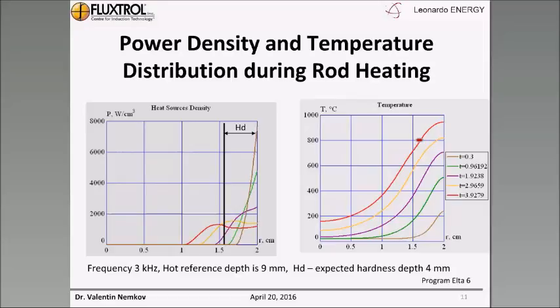Here there is a desired hardness depth, and approximately here we have a point where the Curie point is achieved in the material. Here inside is magnetic material, and outside here is non-magnetic austenitized material. Here there are the corresponding temperature curves, and the final curve shows us that at the hardness depth we have slightly above 800, when at the surface we have approximately 930